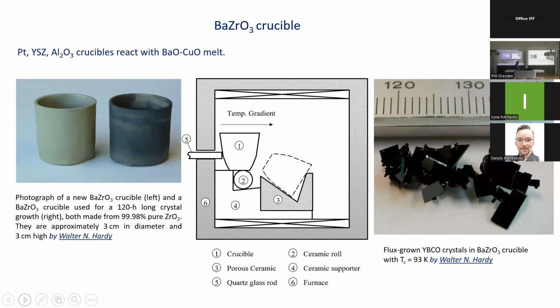So they are small, the inner diameter of this barium zirconium oxide crucible is 2.6 centimeters. It's much smaller compared with aluminum oxide, but nevertheless, people could produce really nice YBCO crystals. The most pure one with high TC, 93K. So it's still possible.